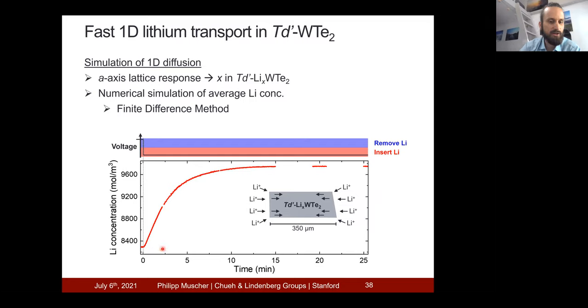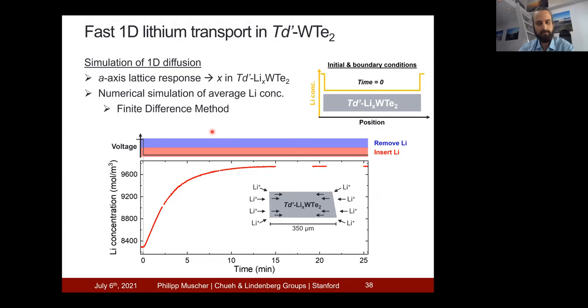So with this concentration over time profile, we can use that to simulate diffusion using the finite difference method. The initial and boundary conditions are chosen in a way that the lithium concentration is always fixed at its maximum level on the edges of the flake. This is because the electrochemical potential is such that lithium insertion is strongly favored. And the initial condition is that at time zero, the lithium concentration is at its minimum level everywhere else.